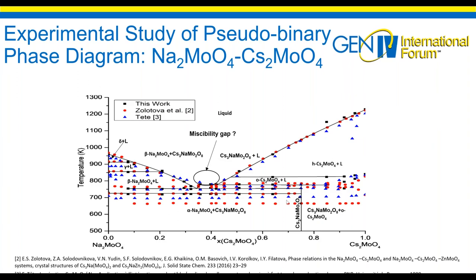So we performed several measurements with different compositions of Na2MoO4, Cs2MoO4. And so we obtain what we call the experimental pseudobinary phase diagram here between Na2MoO4 and Cs2MoO4. And what we have to assess with this is, is there a miscibility gap here? And this type of measurements will be used to build the CALPHAD model and get also a lot of information about the interaction terms L between the liquids.